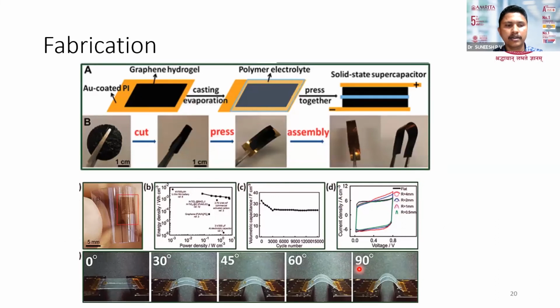And on the fabrication part, I just want to show you how we can fabricate such a device. So you can see here the graphene hydrogel, which is coated on a gold plate, or you can use a copper plate on which you are coating. This is taken from a research article, and they have used the gold plate on which they coated gold film, and on which they coated graphene hydrogel, which is the electrode material. Instead of gold, you can use copper material. And then after that, you have to incorporate the electrolyte on top in the form of a polymer electrolyte.